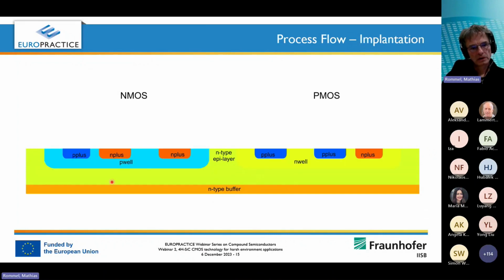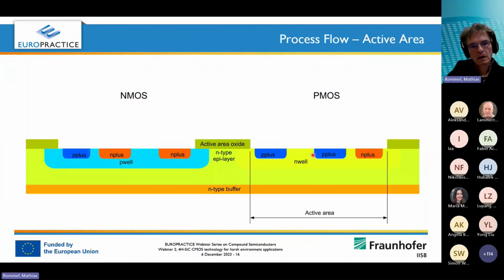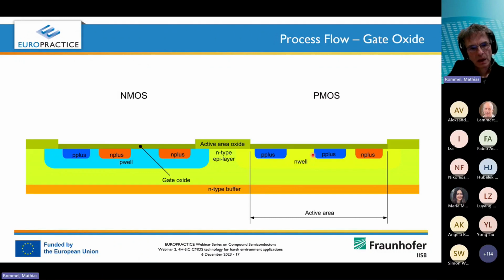Then we do the doping by ion implantation and further high temperature annealing. We have basically all the NMOS in a P-well, and here it's not very well visible maybe, but the PMOS in an N-well, and you also have the according contacts for the body and also for the main transistor here. Then we have an oxide which defines the active area. Then we get the gate oxidation. Still at the current stage, we use a thermal oxide here, a thermal silicon dioxide.